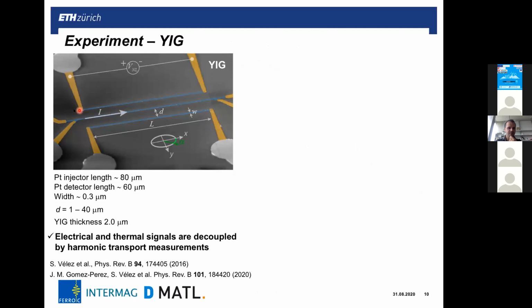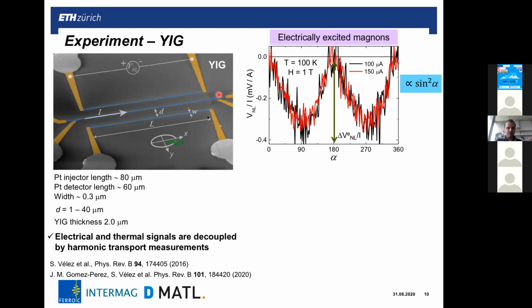So the devices that we investigated are the ones shown here. We have very thin and very narrow layers, and we make devices with different distances and inject current and measure the non-local resistance on this platinum stripe on top of the yttrium iron garnet. You can decouple the electrically and thermally excited magnons by measuring the first and second harmonic response of the signal. Also, the angular dependencies relate to the fact that for the electrically excited magnons, we have both the spin Hall effect and inverse spin Hall effect involved, and this leads to a sine square dependence with angle on the response of the magnon current that we detect in this stripe when we inject the current here.